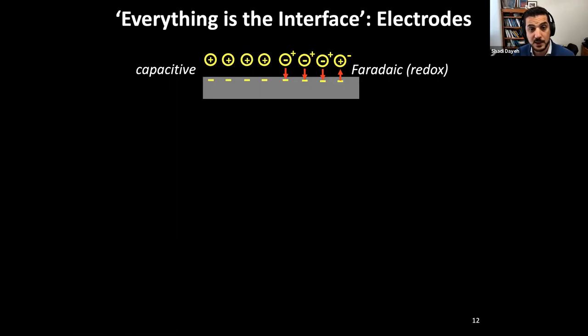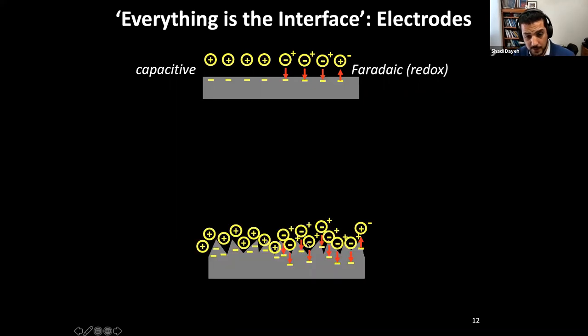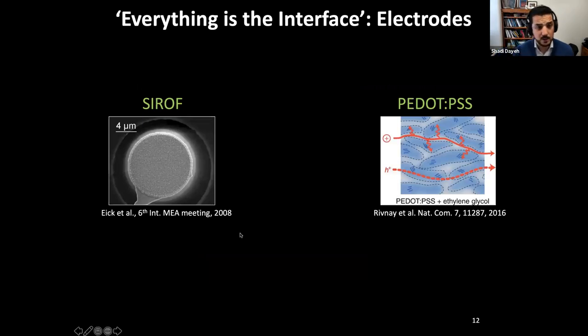Now, this is obviously surface limited, and if we roughen the surface, then we create a larger surface area where we can increase the capacitance. At the same time, we create sharp tips on the rough surface that enhance the electric field, and that facilitates the direct charge transfer or the redox reactions. This has been pursued before with sputtered iridium oxide films. This is an image of something that could be sputtered. It's rough, has low impedance and what's called high charge injection capacity. On the right-hand side, we see PEDOT, and PEDOT is a one-dimensional polymer that has gaps between its polymer chains. So ions can really permeate through the volume of the polymer, and you have volumetric sensing as opposed to surface sensing.